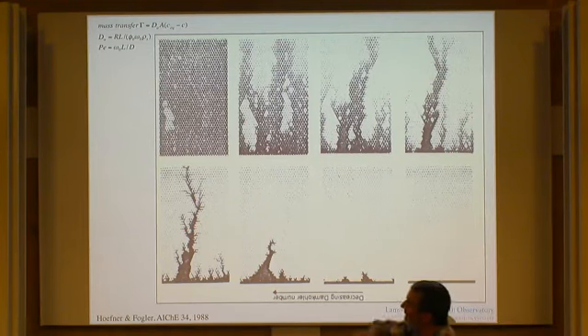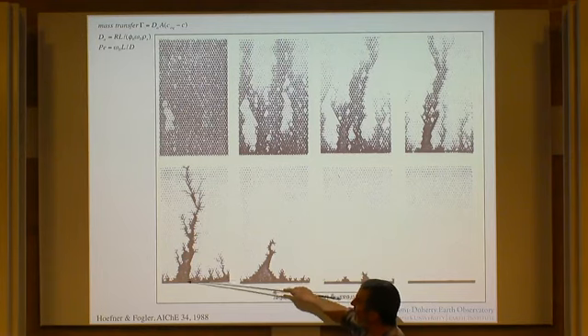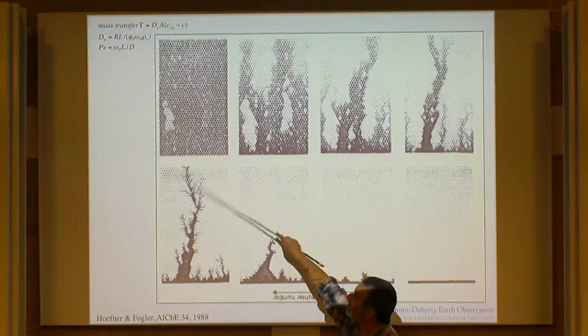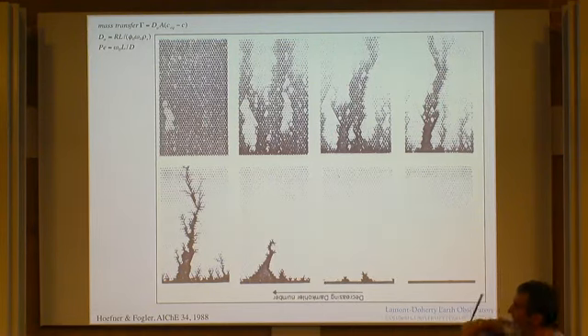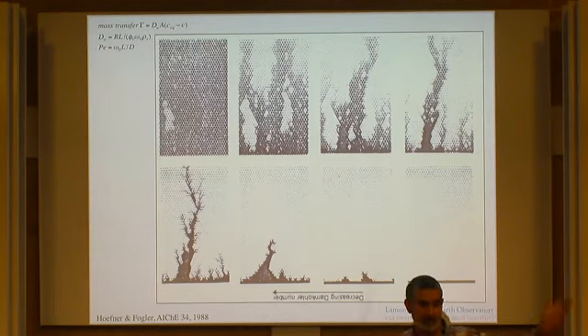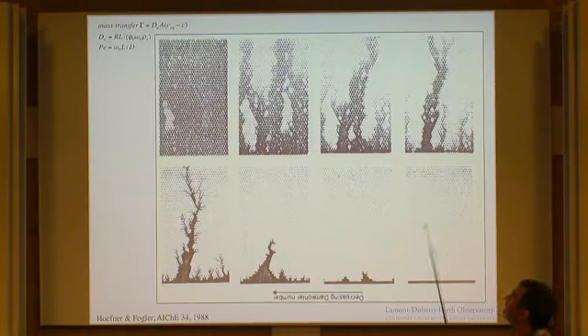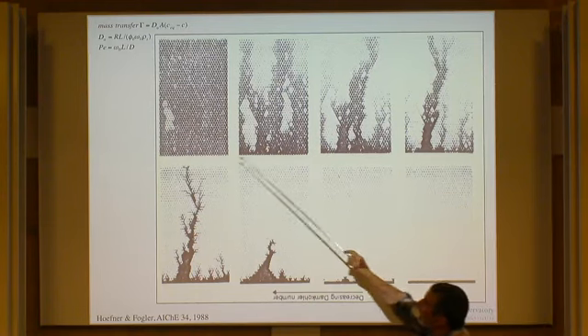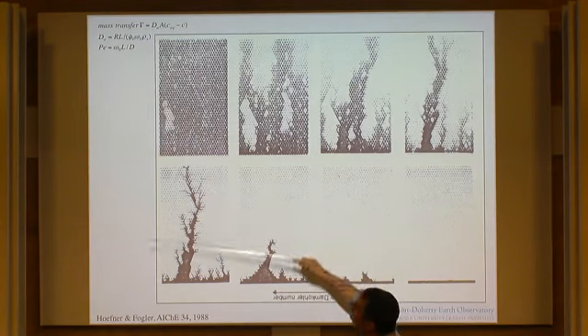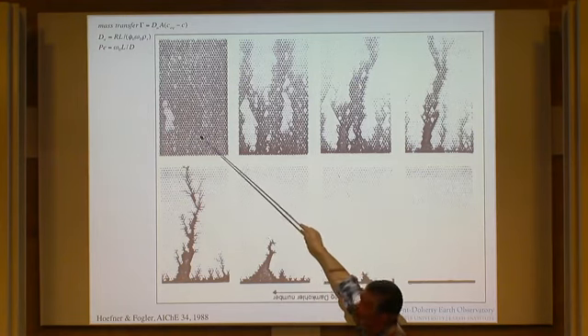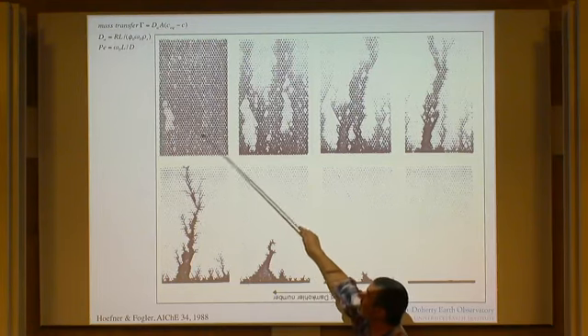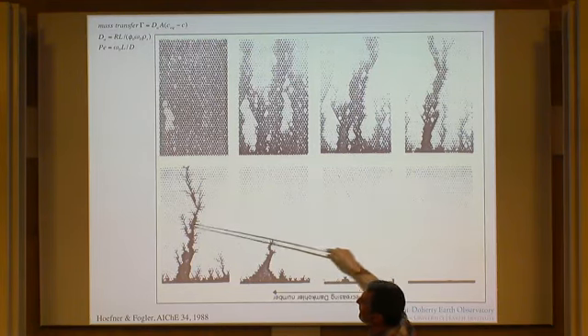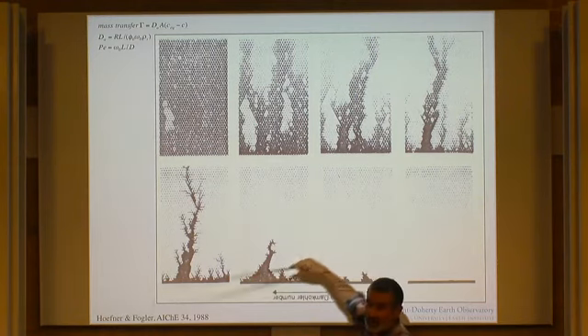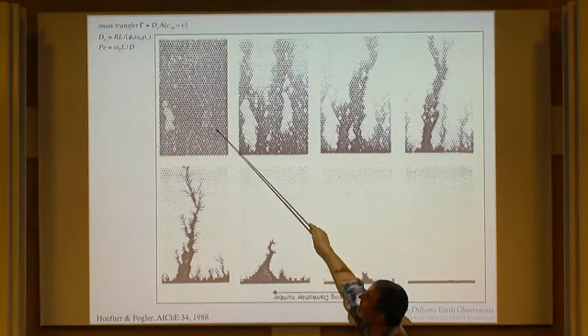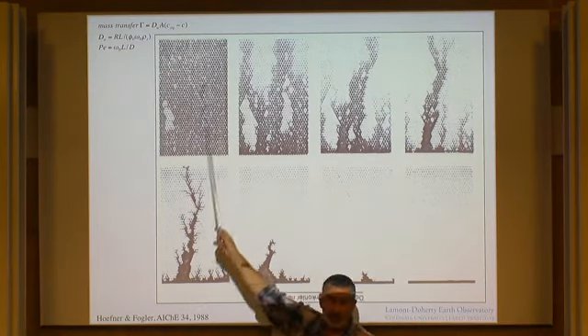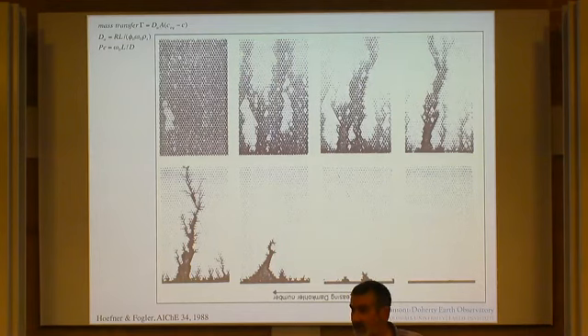At intermediate flow rates, the fluid in the fingers remains strongly undersaturated, and you get these dissolution channels that eventually break through the system. And then they get very big and they starve all their neighbors, things that I already showed you take place. But if you increase the flow velocity still more, then the liquid doesn't equilibrate with the matrix anywhere. It's always a really strong solvent, whereas here, liquid going in the slow path out here is saturated in the soluble phase. But here it isn't. And so every single grain boundary or every single pore turns into a channel, in which case there's no channel.